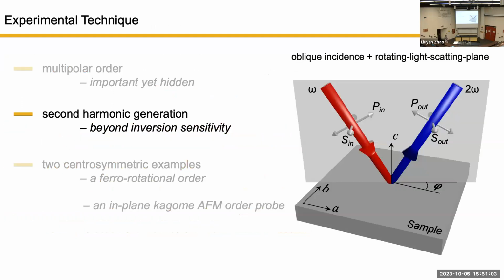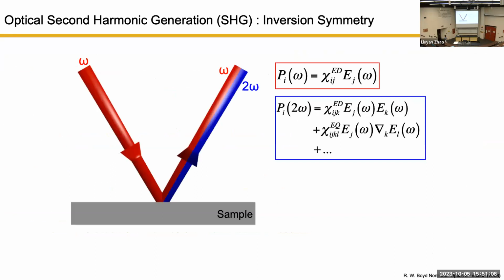Okay, so then we go to our technique itself. As we said, it's a long-standing technique, second harmonic generation. So I have frequency omega coming in. Most of the light coming out is still this linear process, frequency omega. But there's a small fraction at frequency 2 omega and a small fraction at 3 omega, and so forth. We only care about up to 2 omega here. And for us to pick out the 2 omega, we just use optical color filters to suppress that omega. So the weaker my 2 omega, the better suppression I have to do for the first omega.